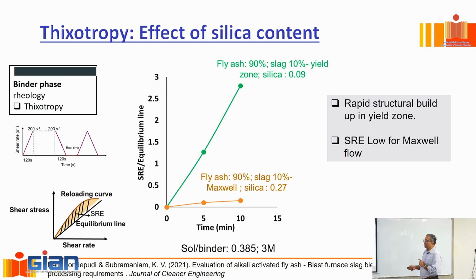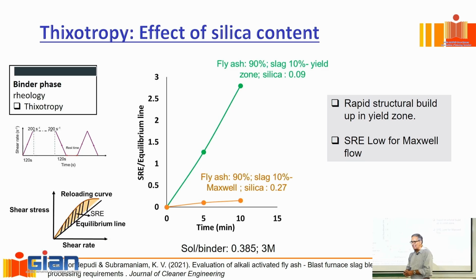What do you notice as the difference here? At 0, both are similar, which is basically where I am down. I wait for 5 minutes. This fellow doesn't structurate enough, whereas this fellow is structurating, right? If you look at 10 minutes, this fellow is still not structurating enough, but this fellow is, right? So if I was to print with this fellow with high silica content, what would happen? So remember, this stage here represents what's happening during pumping. When it's going through the pipe, when it's going through the nozzle, it's getting sheared very much.